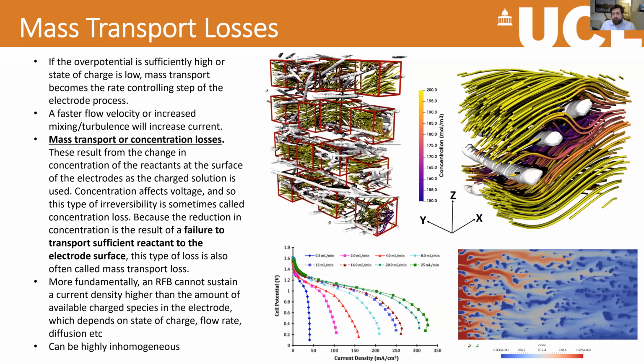And also, as I said before, this depends on the flow rate as well and the flow properties in RFBs. And the flow rate also incurs a parasitic power loss. So we have to use pumps to flow our electrolyte through the system, and they require a certain amount of power. And obviously, if we have electrodes that have lower resistance to this pumping, have better mass transport properties, then we can reduce that parasitic pumping loss as well.